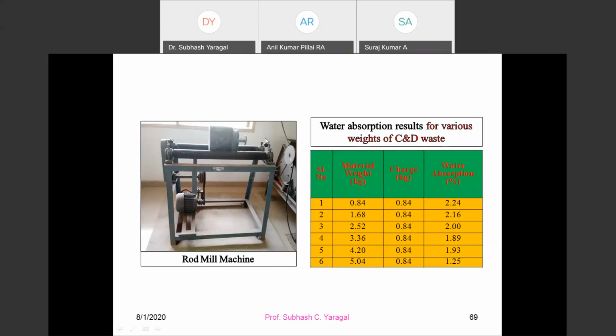So we thought, why not use this rod mill to process the recycled coarse aggregate from construction and demolition waste. This study is very interesting. We have optimized three parameters in this study. Now, how do you say your recycled aggregate processing is good? That is based on a simple test, the 24-hour water absorption test on the processed coarse aggregate.